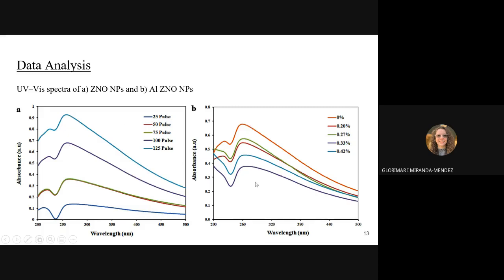However, in the doped zinc oxide nanoparticle UV spectra, we observe this trend, but only when we compare the 0.2% and the 0.27% with each other, and the 0.33 and the 0.42%. They conclude a possible theory in which the lower percentage of the dopant ratio has a higher percentage of absorbance. This they associate with the possible scattering of the nanoparticles, and also possibly the aluminum reflectance that causes the higher percentage to appear at a lower absorbance.